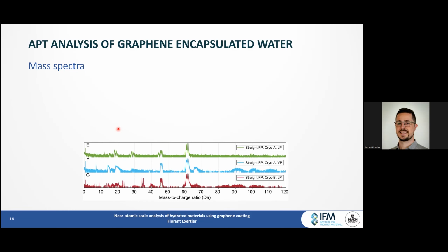For cryo scenario B, the absence of peaks containing carbon, so at 12 or 28 or 29 with CO and COH, seems to confirm the successful removal of the outer graphene layer, which is in the film.